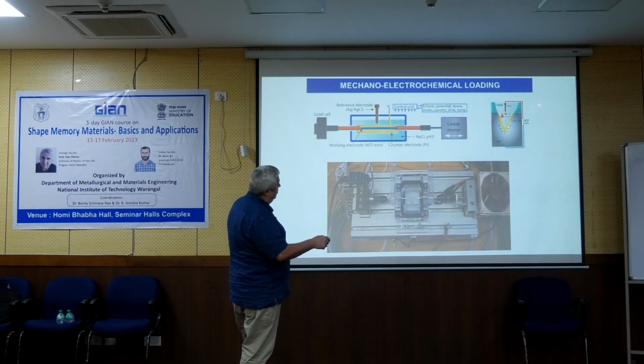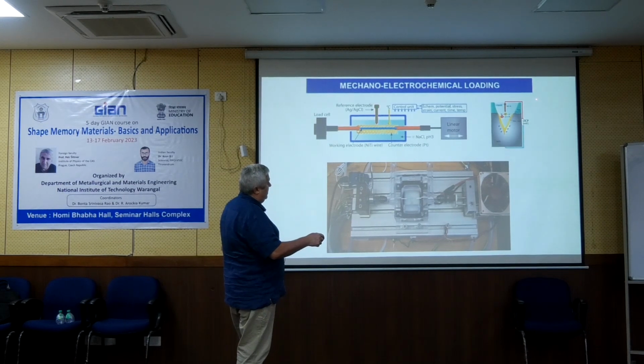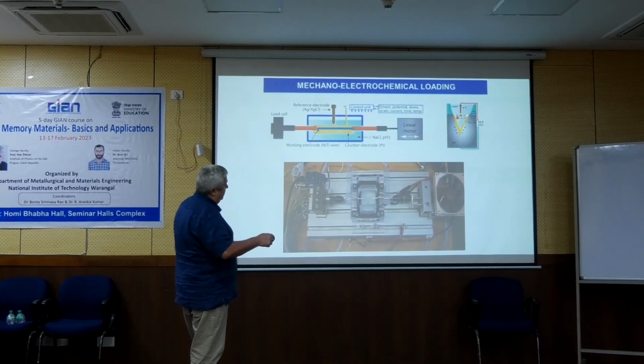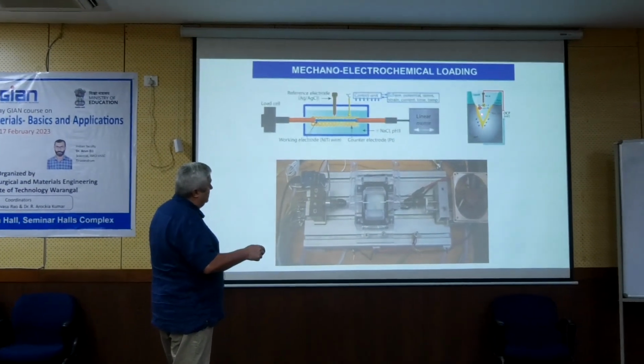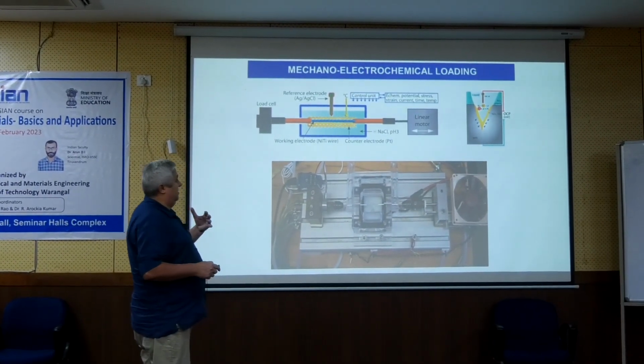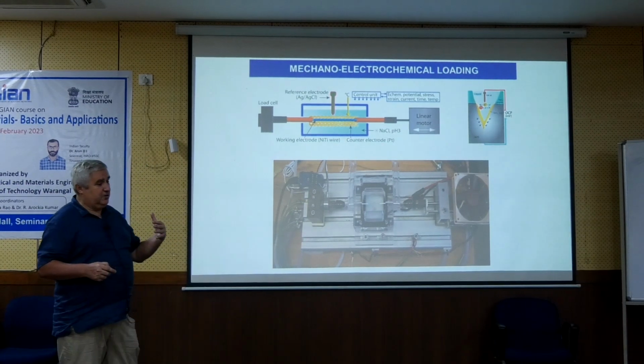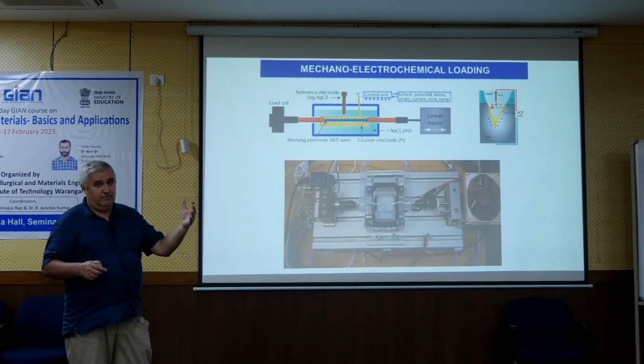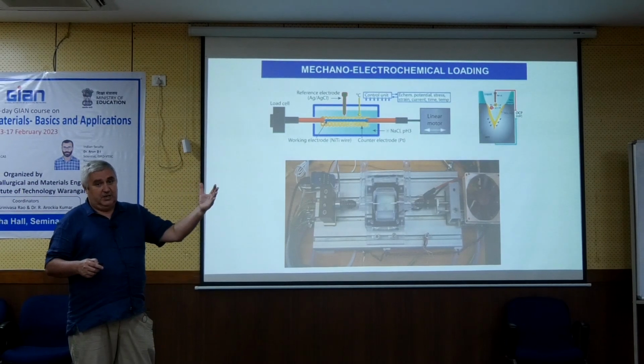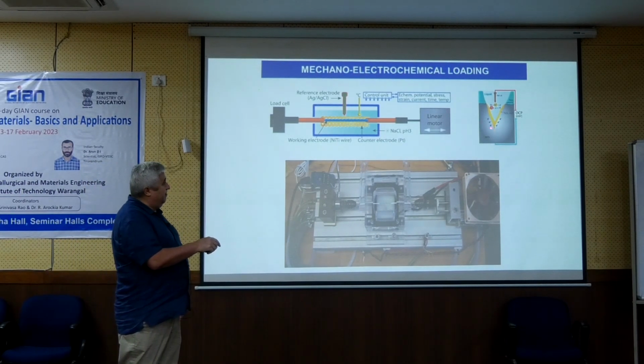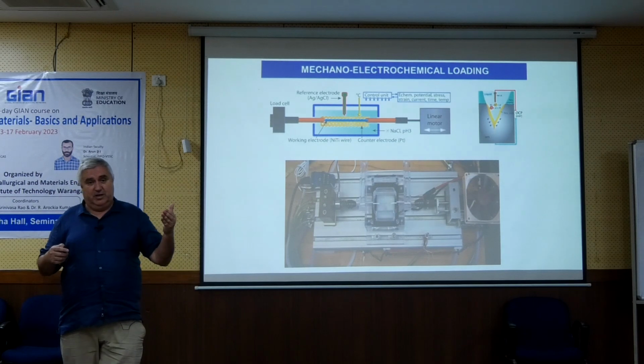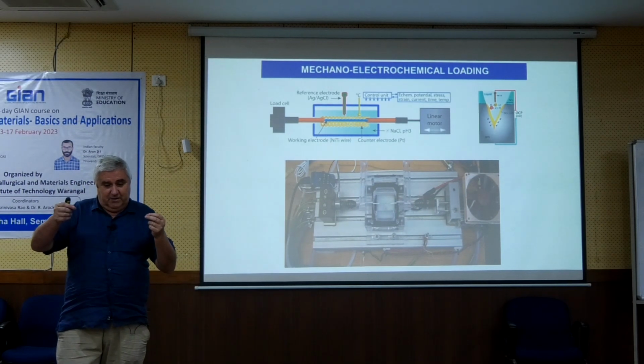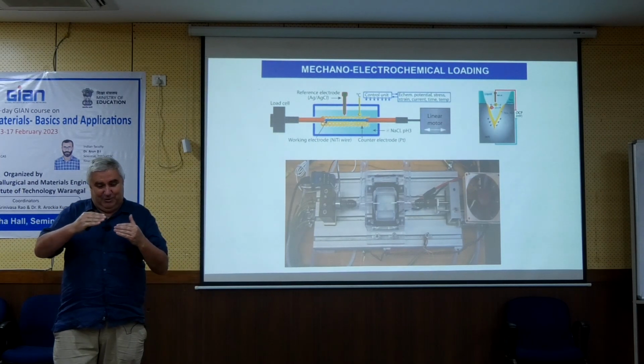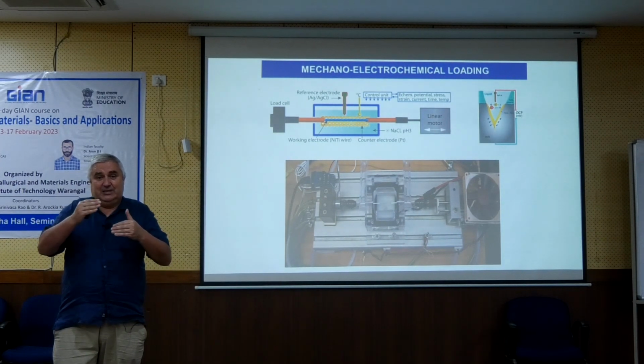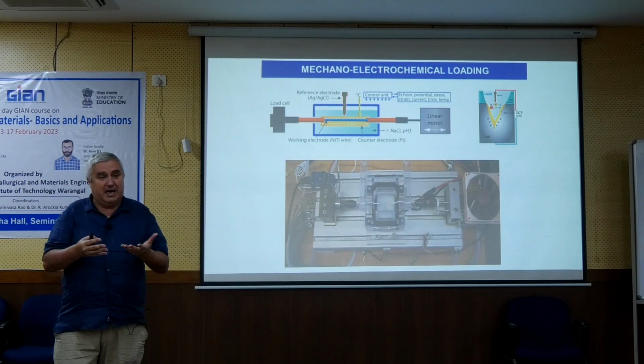There is this blue, which is titanium oxide, and here there is a crack which opens, and by the blue color, this is also titanium oxide, but a very different one from that which is created by oxidation. This one is created by the electrochemical reaction. Because even if we measure the OCP, if you have the metal in the fluid, there is immediately the electrochemical potential, and this speeds up the corrosion process.